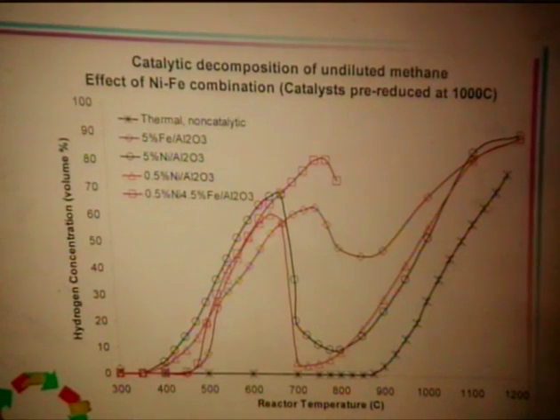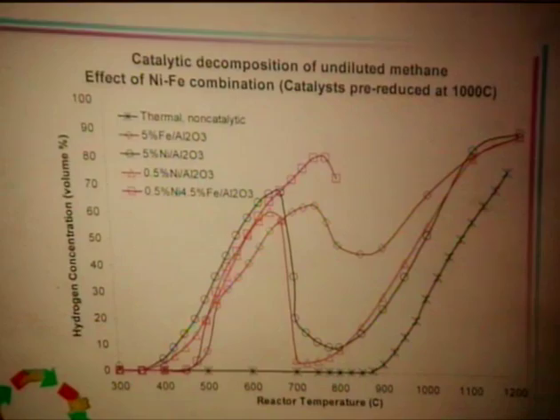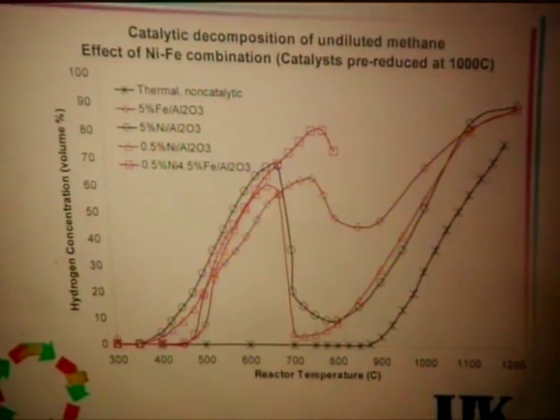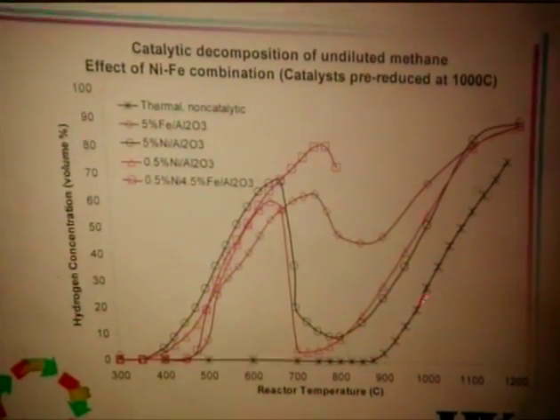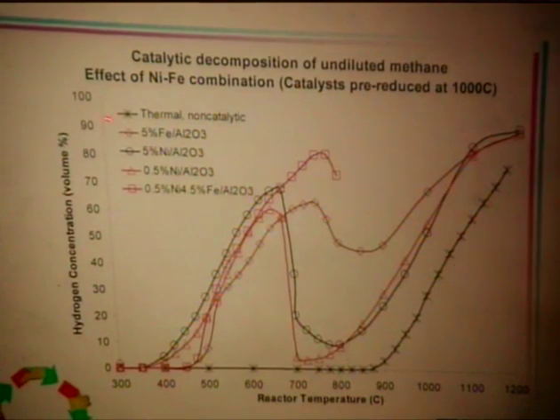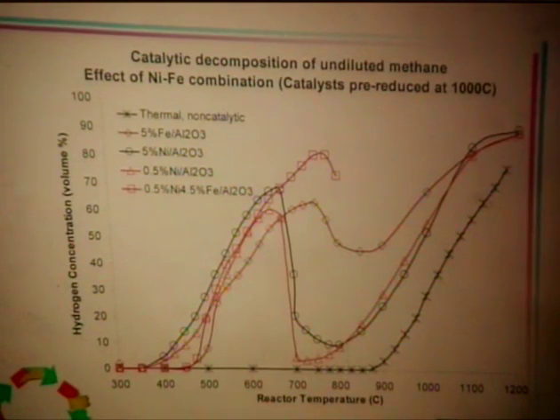Here is the nickel and iron based catalyst, binary as well as monometallic. This is the thermal cracking curve, and we have used 5% nickel, 0.5% nickel, and the binary catalyst. The binary catalyst shows better activity. All these catalysts were pre-reduced at 1000 C. Here we stopped the reaction because of clogging of the reactor.